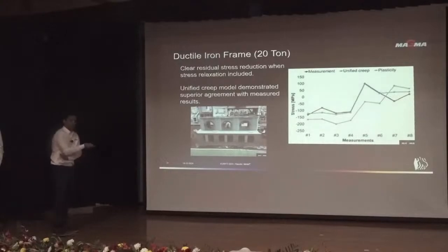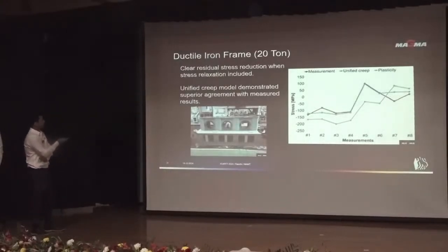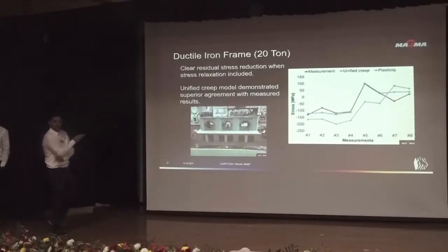After learning from the previous example, we took another case of a ductile iron frame. What we did was clearly point out the places where we are going to use those gauges. What we found was that the unified creep model demonstrated superior agreement. The curves that are matching demonstrate the creep model results.